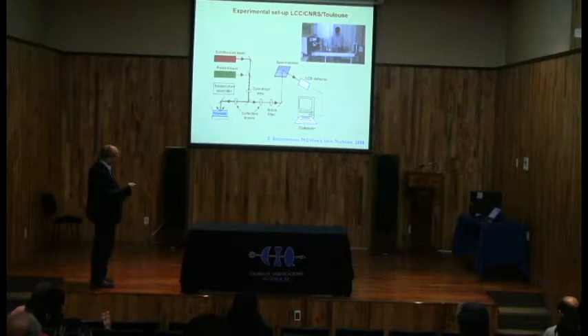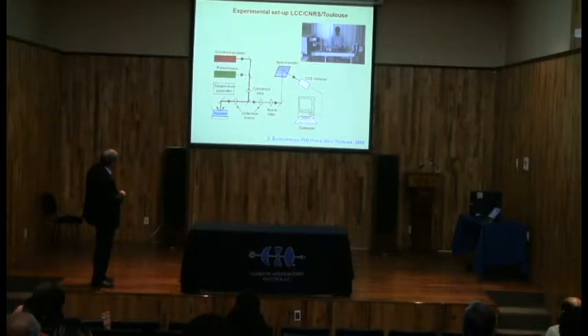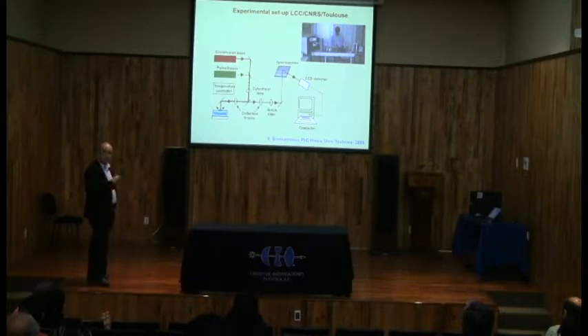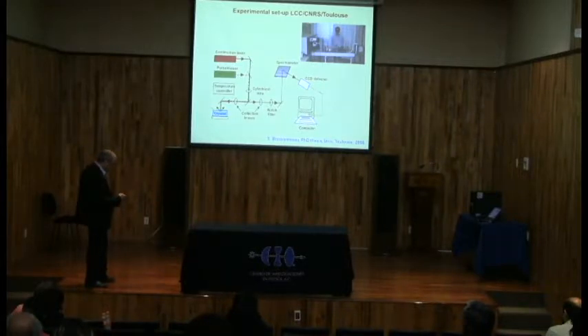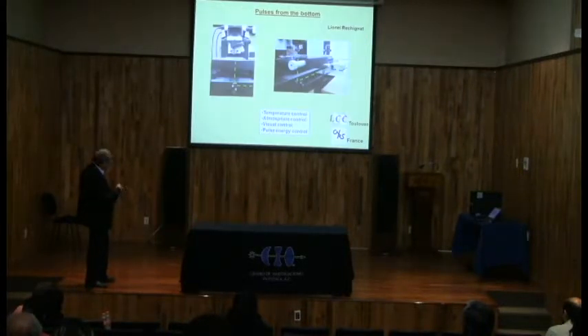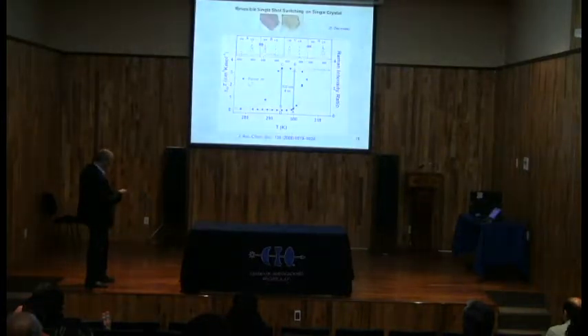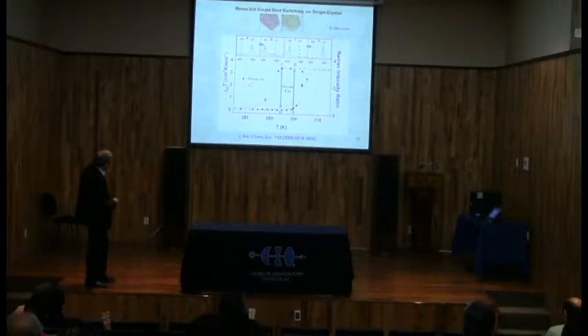So then we did these experiments. We took two lasers: red for measuring the Raman spectroscopy, and pulsed green light to send the energy to switch the system. So we have this protocol in order to do these experiments. Okay, so here are the experiments. As I told you, we have to look at 4 places here. Here it's low spin, here it's high spin.